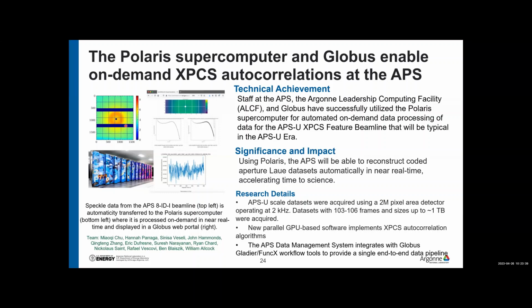So you illuminate a sample with coherent light. This system scatters, and in the far field, you collect this scattering pattern on a detector. And if you do that at different time intervals, and you look at the correlation and the fluctuation of the intensity as a function of time, and you look at the autocorrelation between these time series, you can reconstruct the dynamical structure factor in the time domain. So it's a way to do spectroscopy in the time domain rather than in the frequency domain, which is usually associated with scattering techniques where exchange of energy happens.